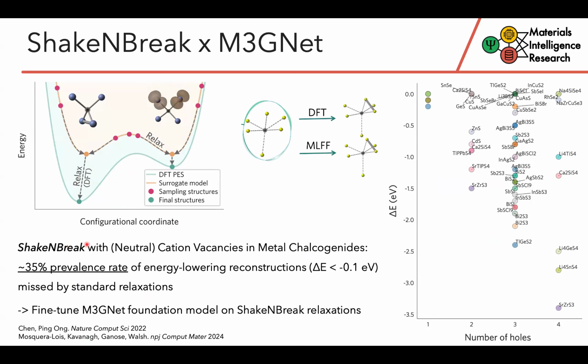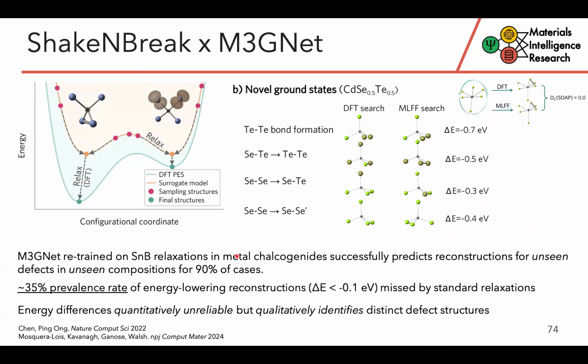So we first applied ShakeNBreak to a set of neutral cation vacancies in metal chalcogenides, where firstly we found this 35% prevalence rate of significant energy-lowering reconstructions that are missed by standard relaxations. So you can see here on the right, in many cases these are very large energy differences you get for these particular defects when you use ShakeNBreak compared to just a normal unperturbed relaxation. Then taking the M3GNet potential and fine-tuning it on this set of hybrid DFT relaxations, we found that it was able to successfully predict these energy-lowering reconstructions for unseen defects in unseen compositions for 90% of cases here.